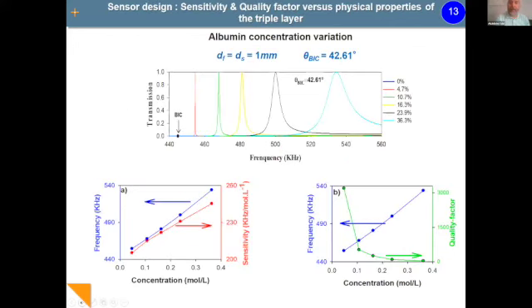This configuration was used to design the sensors. We take a configuration with a given geometry, starting from 0% when we have only liquid. We add albumin concentration, and we see that directly the resonance appears. When we increase the concentration, the frequency shifts to high frequency, and the width of the resonance increases. We have sensitivity, and the quality factor presents its maximum value near the bound state.